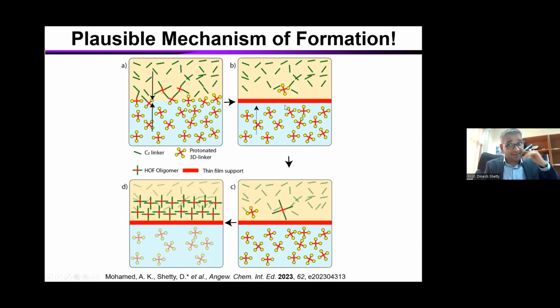Once it is going, fewer building blocks reach the upper layer, and at the same time you opened it, okay? When we partially open, what happened? The upper layer has the organic layer, right? It started evaporating, and the concentration of the other monomer increased drastically compared to here, right? That leads to the formation of these 1D crystals, and they slowly stack, come together, have very strong hydrogen bonding, and then they form that film.